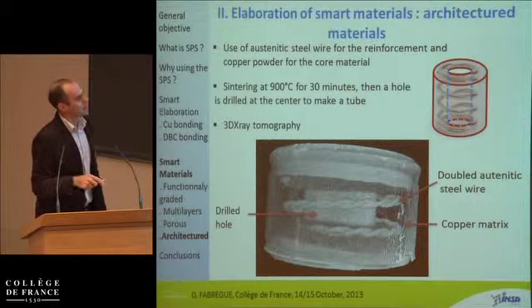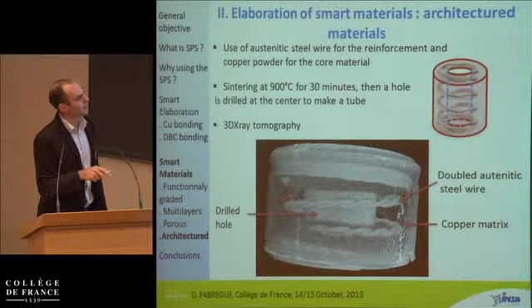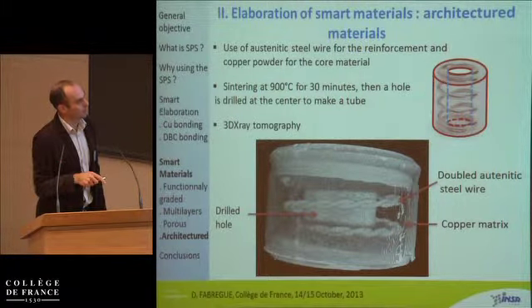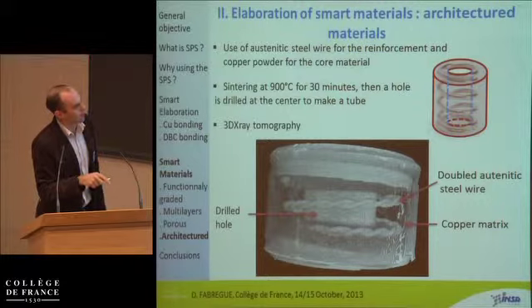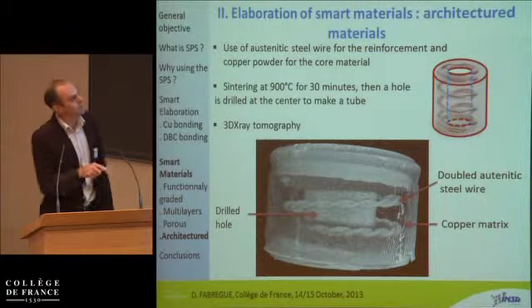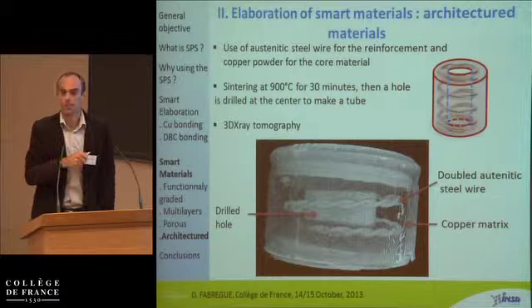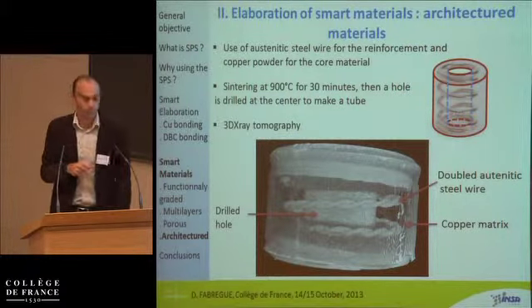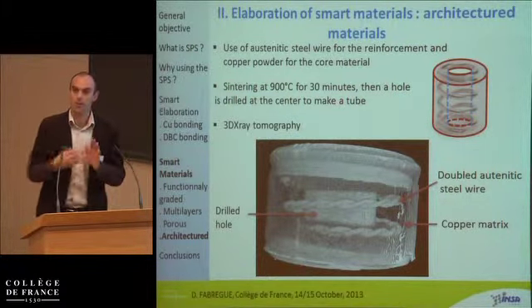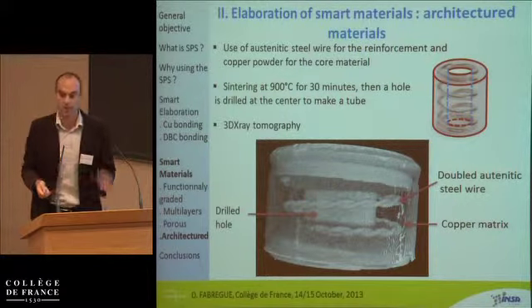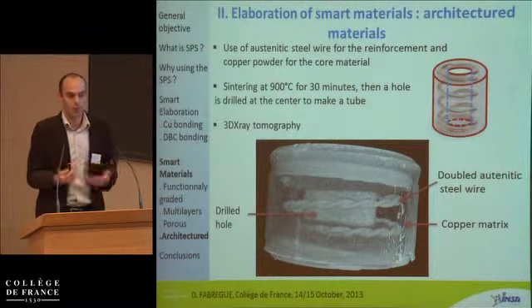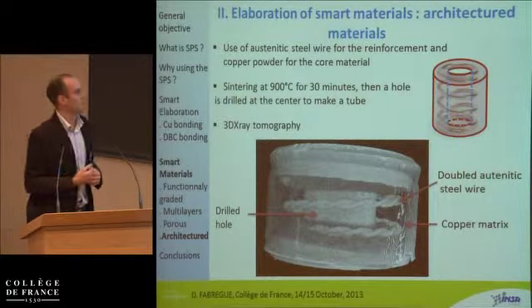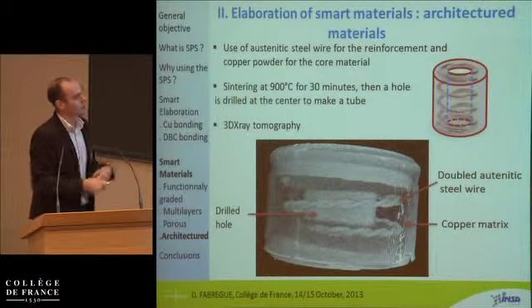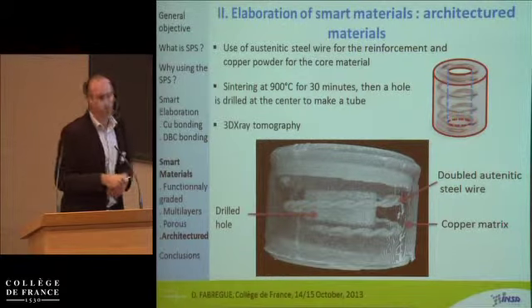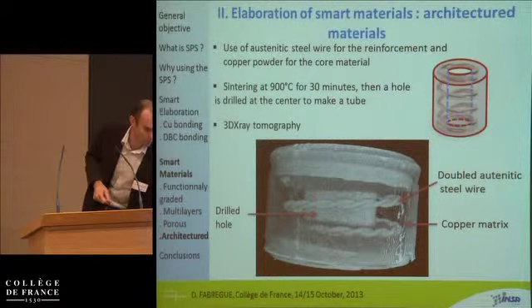And so this is an X-ray tomography. You see the steel wires going like this, and this contrast. Let's say the black one is the copper, the white one meaning no absorption. That means this is a drilled hole, and so you have exactly this kind of structure. We looked at the interface also, and I can say to you that we have diffusion of the copper inside the steel and the steel inside the copper. That means the strength of the interface should be okay. So that's one of the examples of funny things you can do with a spark plasma sintering system.